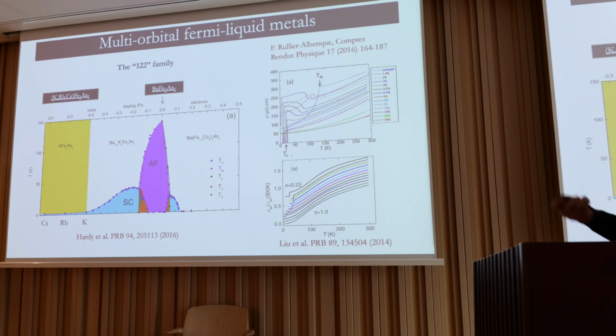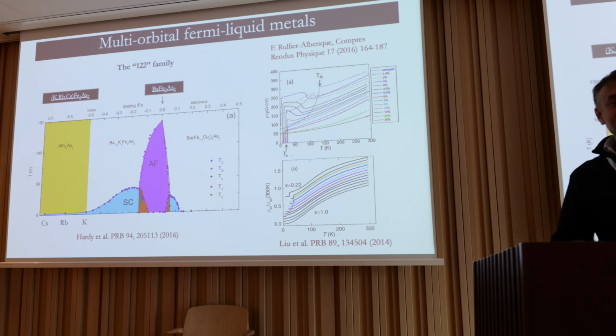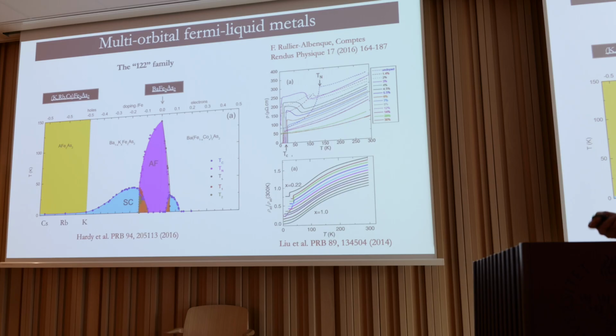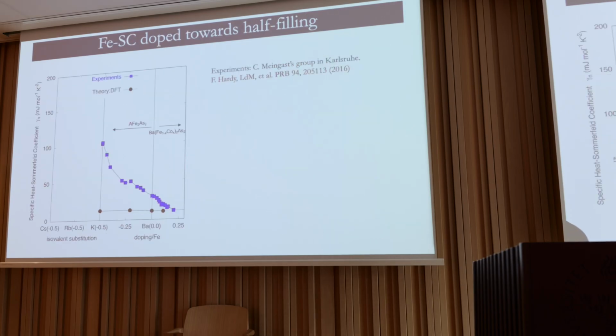However, Fermi liquids have effective masses, and these effective masses do something really interesting. If you look at the Sommerfeld coefficient along the family, it goes up and up and up - these blue points. And if you do DFT, it's basically constant.